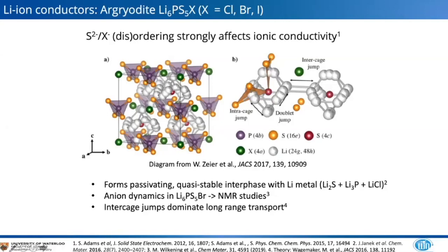This is shown by Jurgen Janek in a nice paper, and he's going to be talking about that a bit more. And there's also been anion dynamics investigated, polyanion rotation. So there is an intercage jump in this material, which is thought to dominate long-range transport. So disorder on either of these two sites will determine the ion conductivity. And if we have iodine in the lattice, the iodine is localized on the 4a site, whereas sulfur is on the 4c site, whereas in the case of chlorine and bromine, there's delocalization over those two sites, and that gives rise to very high conductivity.